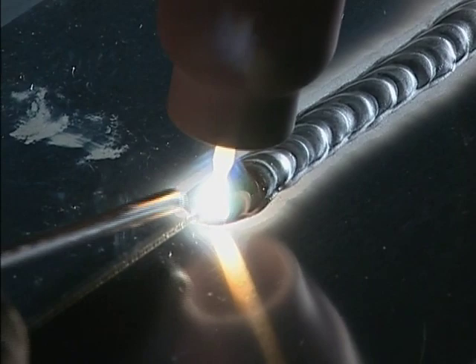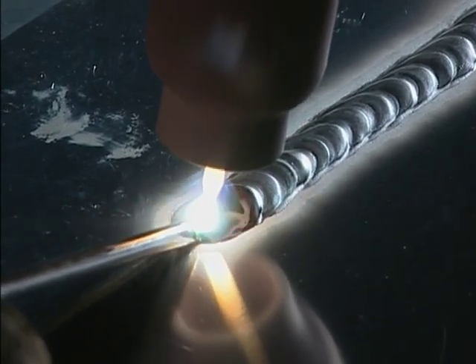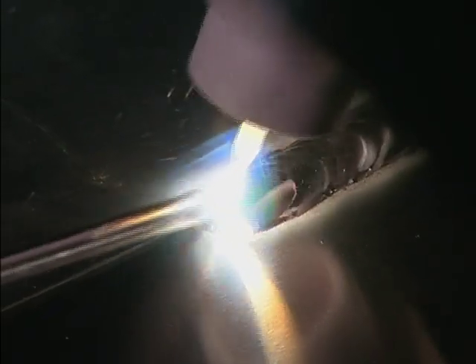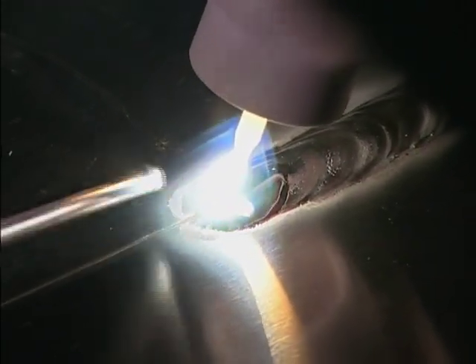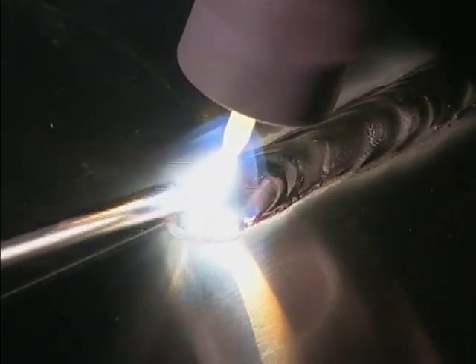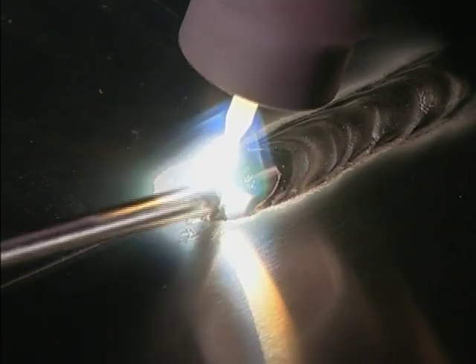The plate temperature rises as you approach the end of the bead, and you run the risk of burn-through and bead width expansion. Accommodate this risk by gradually increasing both torch speed and the pace of filler rod feeding.